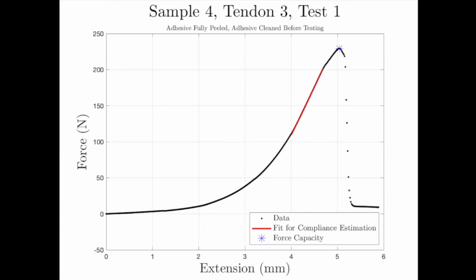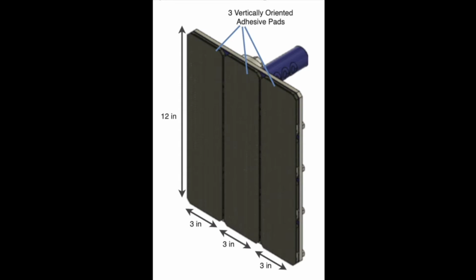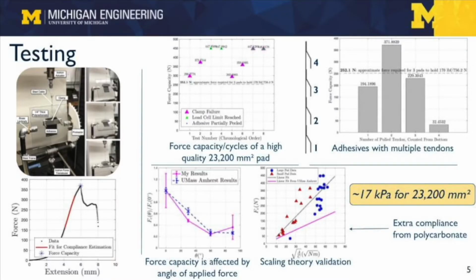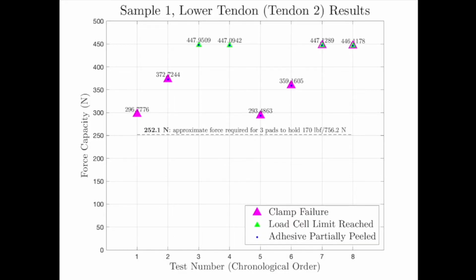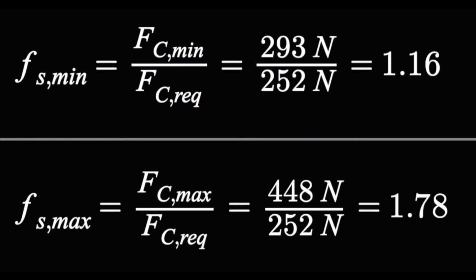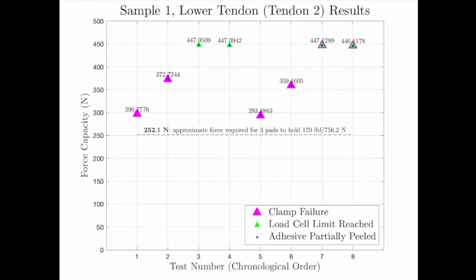My pilot testing with a smaller adhesive pad led me to hypothesize that three 3-inch wide by 12-inch long adhesive pads holding a load in parallel could be enough to hold my weight of around 756.2 newtons, meaning that each pad would have to hold around 252.1 newtons. All tests of a good quality adhesive surpass this measure, with the minimum safety factor being 1.16. Additionally, after 8 cycles of loading, removal of the adhesive, cleaning of both surfaces, and replacement of the adhesive showed no significant decrease in force capacity, something that could not be achieved with standard glue-covered wet adhesives like tape.